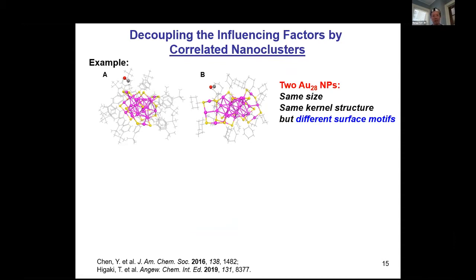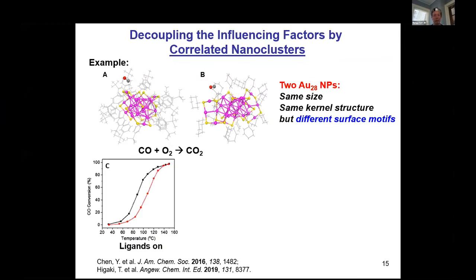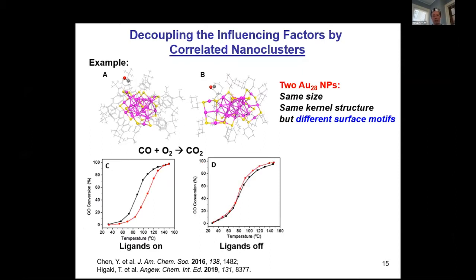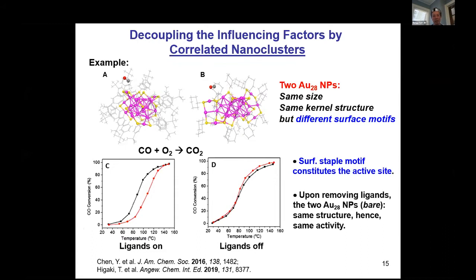We call it a correlated pair. So here we have 2 kinds of gold 28. They have the same size, 28 atoms, and the same inner core structure. But the only difference is the surface structure. So here we can use a very simple reaction, carbon monoxide oxidation, as a model, right? So you can see they have different catalytic activity with the ligands on. But if you remove the ligands, they become the same. That kind of makes sense, because if you remove the ligands, the bare gold 28 will adopt the same structure. That's the beauty of what you're going to be able to achieve by designing such correlated nanoparticles. And so we can eliminate those entangled factors and just focus on one factor.